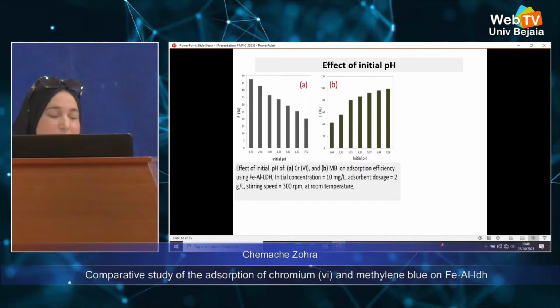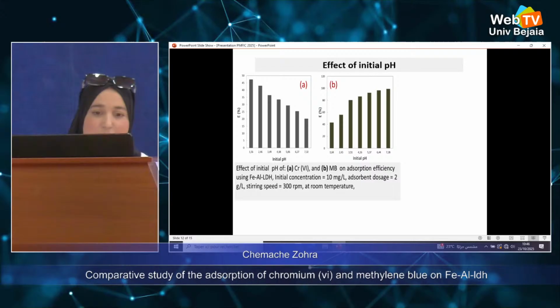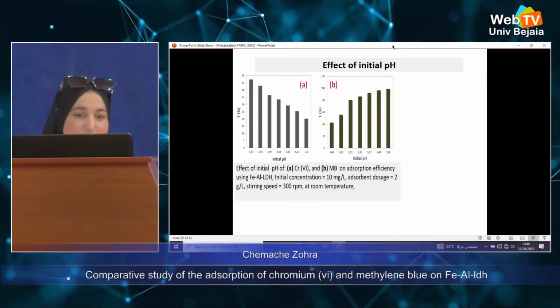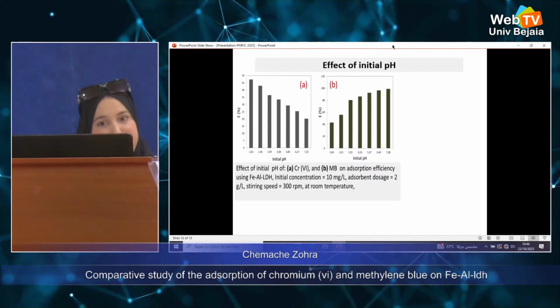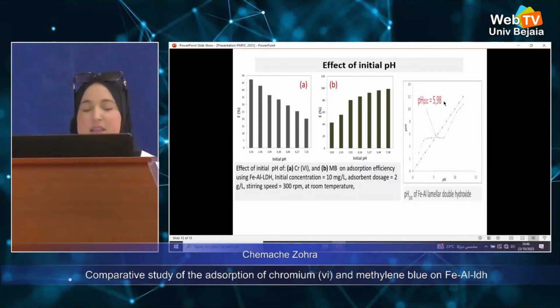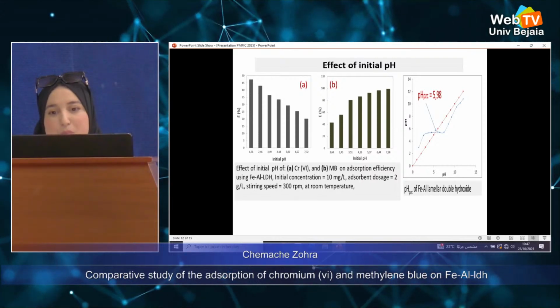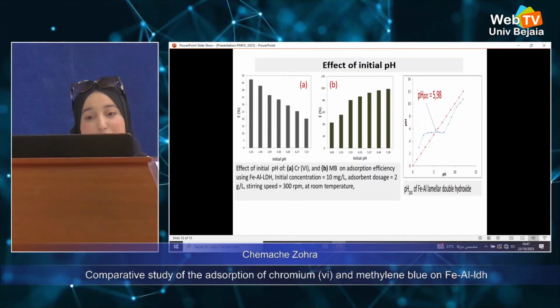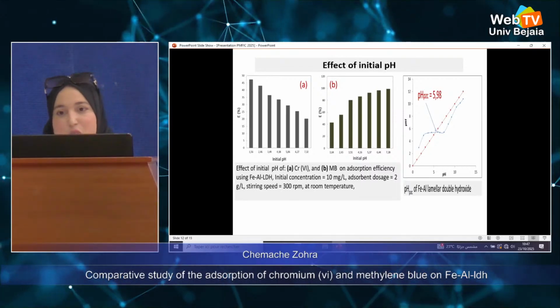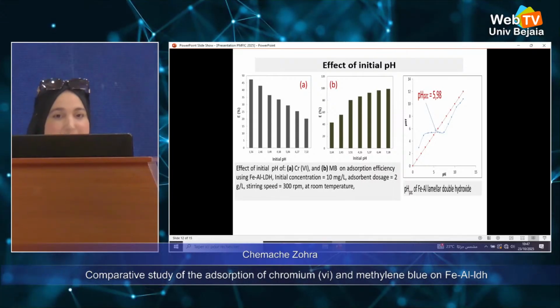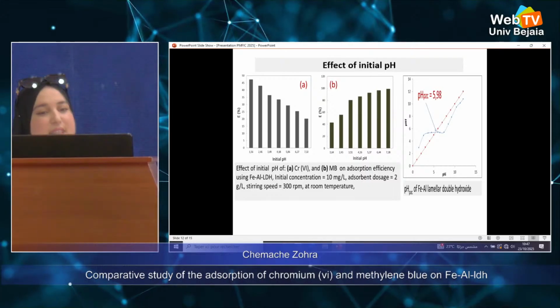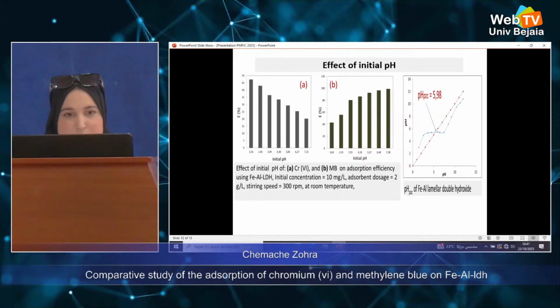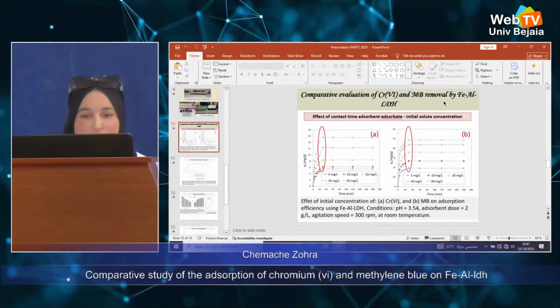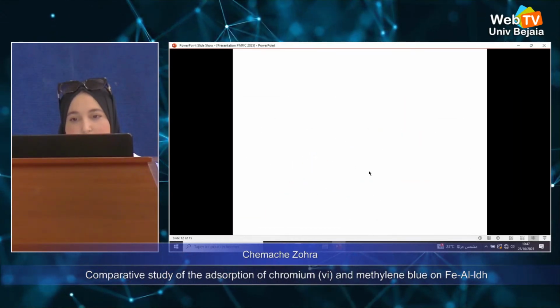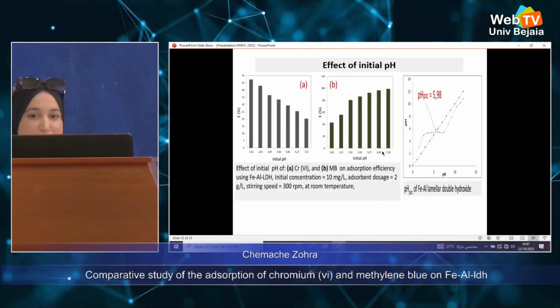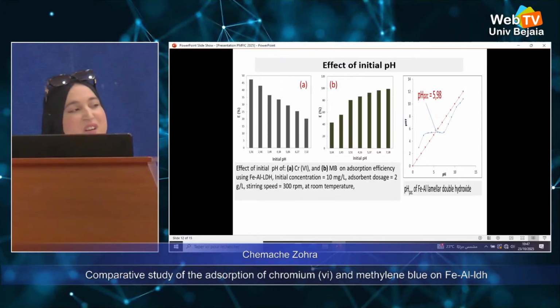This behavior is attributed to the fact that at pH 1.56, the chromium hexavalent species present in solution are anionic in nature. Given that the pH at zero charge is determined to be 5.98, the adsorbent surface is positively charged under these acidic conditions. Moreover, the adsorption process observed in this study appears to be governed by electrostatic attraction.